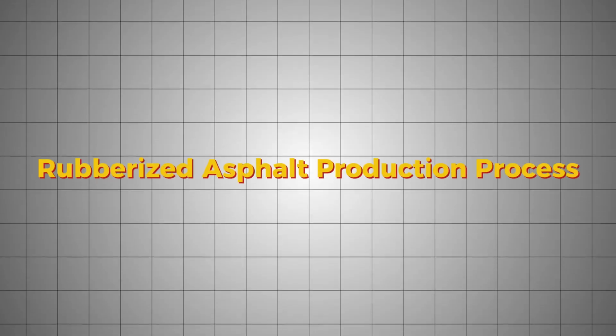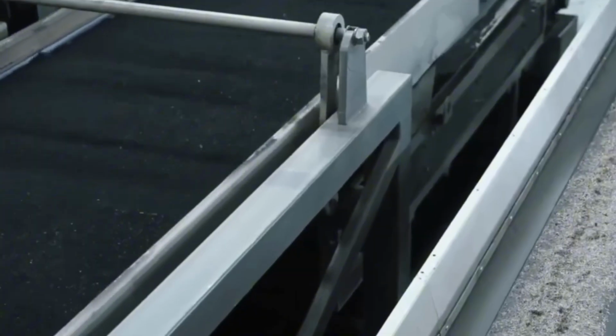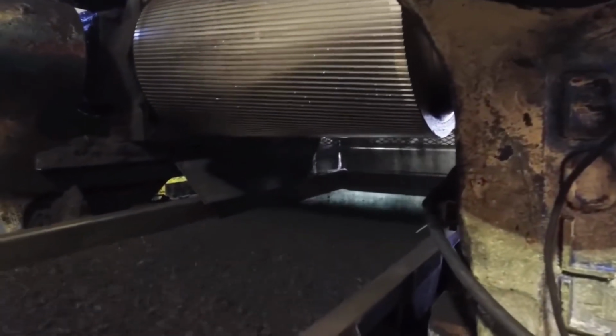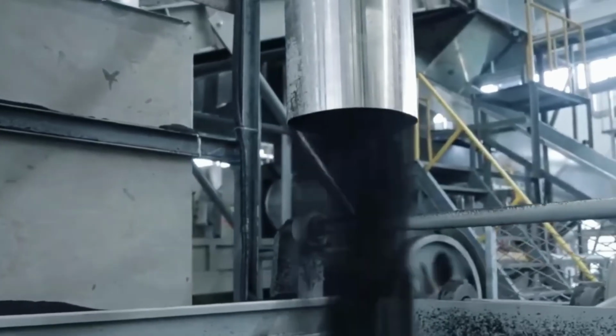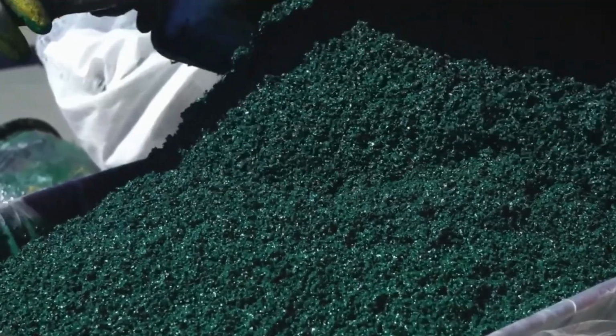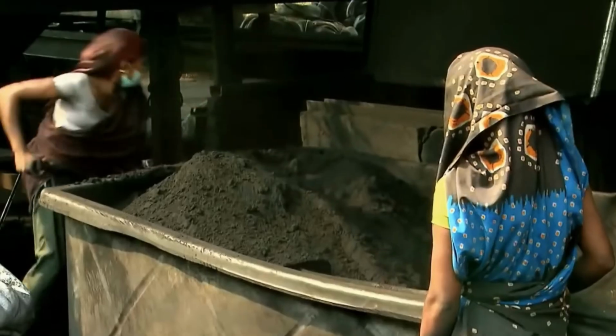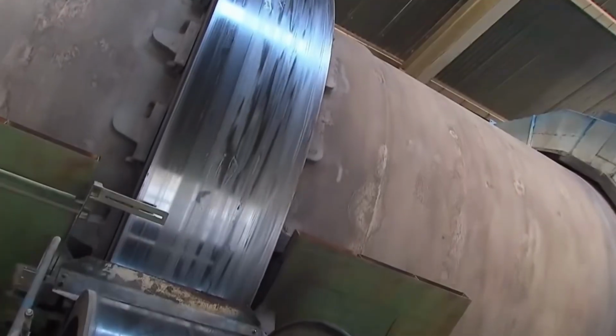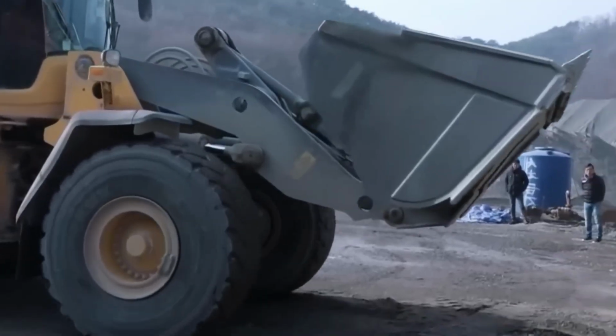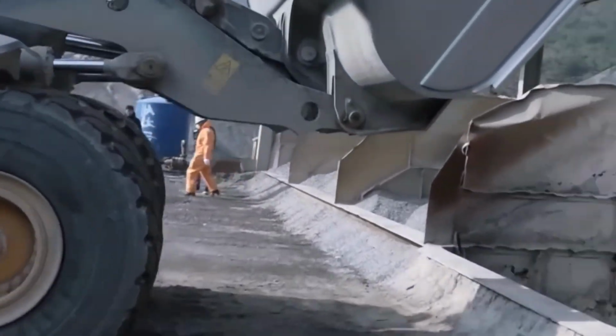Rubberized asphalt production process. After crushing and screening, crumb rubber from waste tires still holds residual moisture, fine dust, and traces of embedded impurities. These elements interfere with how rubber interacts with hot bitumen, limiting bonding strength and preventing the stability required for high-performance pavement. Before blending into asphalt, crumb rubber must pass through a dedicated drying and heating stage.